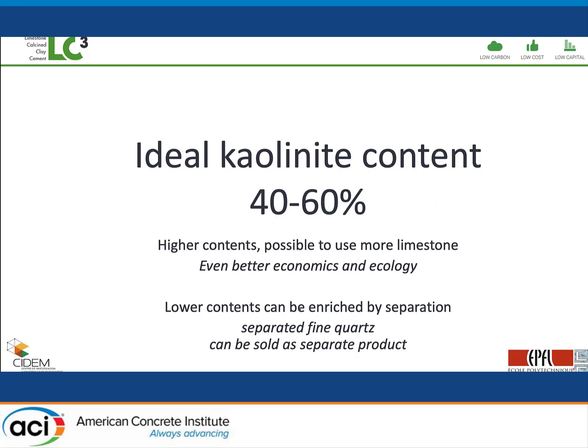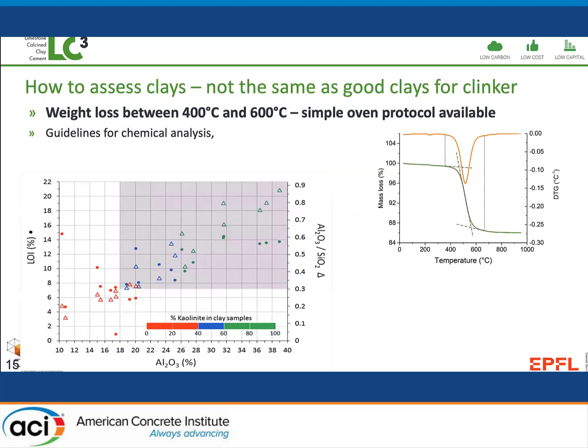And if you have lower contents, particularly quartz is often a mineral that's present, then it's quite a good idea to look at separating it out. So we saw the presentation this morning from Penn State. I think from a practical point of view, using surfactants is going to turn out to be a little bit expensive, but even dry separation, you can get pretty good enrichment. So this is just another way of translating this kaolin-like content to a rough idea of the amount of alumina.